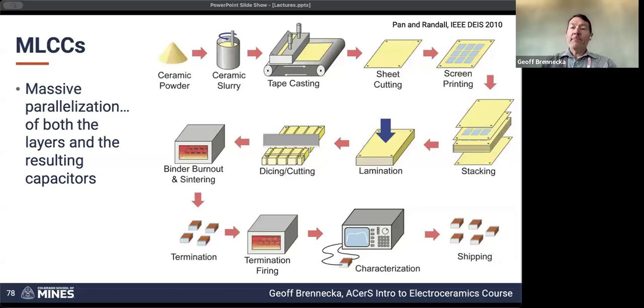So then we'll go through a lamination step. This lamination step is unbelievably underappreciated. You start off, you heavily engineer the process to get the tape made in the first place, and now you've got discrete layers. You've put your screen printed electrode layers on top of it, and you're stacking it up. But you have to get all of these layers to stick together. And so that lamination process helps these layers stick together.